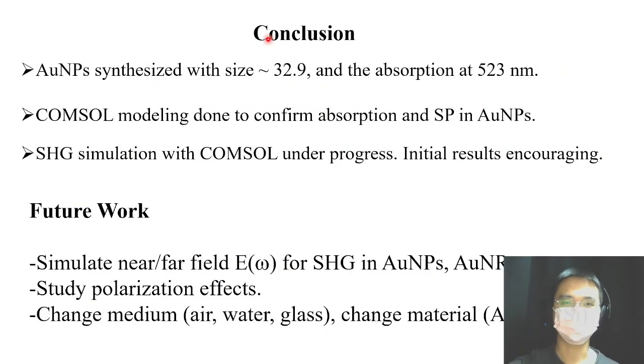And then my conclusion. Gold nanoparticles were synthesized with a size around 32.9 nanometers, and the absorption is at 523 nanometers. COMSOL modeling was done to confirm the absorption and surface plasmon in gold nanoparticles. Second harmonic simulation with COMSOL is in progress.